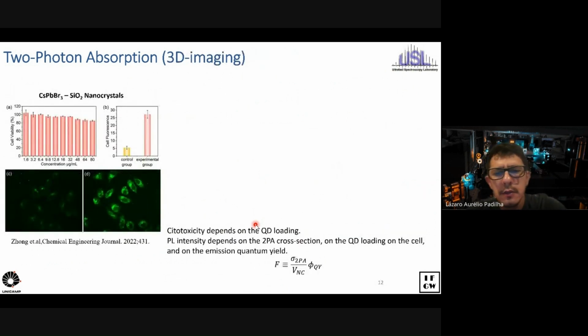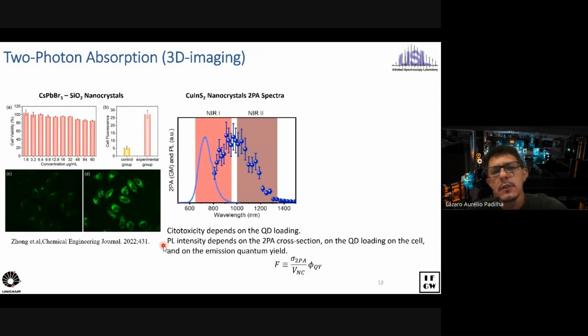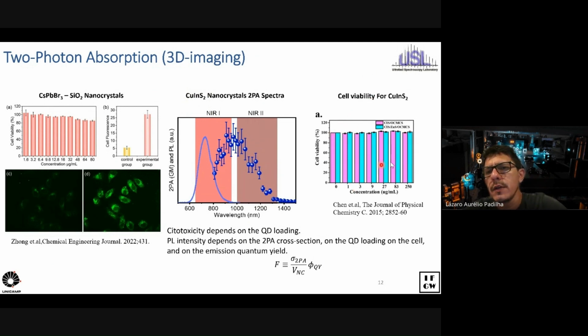Also, people have been doing a fair amount of work looking at two-photon absorption to enable 3D bioimaging. For example, people have been looking at perovskite quantum dots covered by silica to mark cells. Other very interesting materials on this end are, for example, copper indium disulfide, because they're free of heavy metal and have a much better cell viability. If you compare copper indium disulfide with perovskite quantum dots, you can see that CIS can reach basically 100% viability, while even when you cover the perovskite quantum dots with a silica layer, the cell viability drops as you go to high concentration.